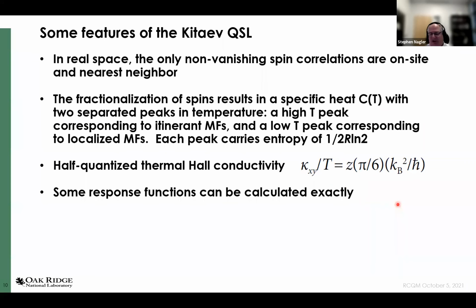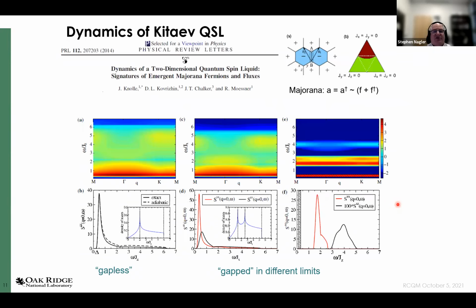Now, the other thing is, it's an exactly solvable model, and it's also possible to calculate some response functions exactly, for example, chi double prime of Q and omega that one measures in neutron scattering approximately, and some response functions for Raman scattering and so on. So here's an example of the imaginary part of the susceptibility calculated in a few different limits in this paper. And you can see here's in the gapless limit. What's kind of interesting is in the gapless limit, the response function at a given value of Q, this happens to be Q equals 0, shows a gap. That's because you create these static, if you like, massive gapped visons or gauge fluxes, and then a kind of continuum corresponding to the free Majorana fermion.